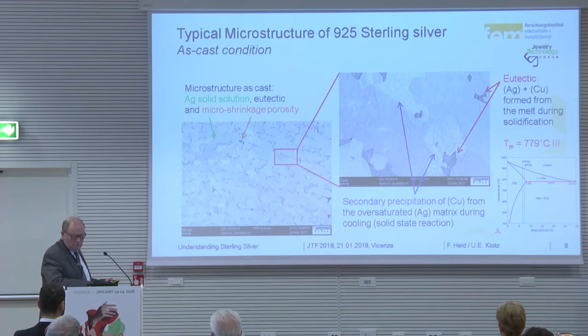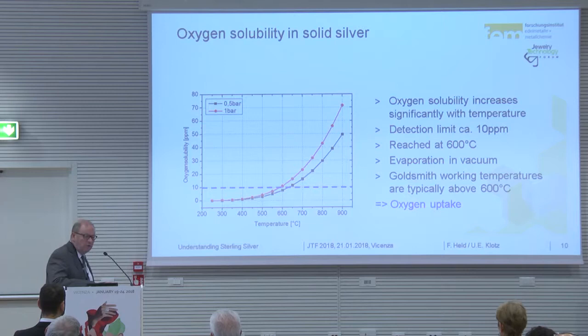What we most use is to look at how oxygen can be soluble in solid silver. We have the blue line here, which is what we can normally analyze. We can only analyze if the oxygen is higher than 10 ppm. If it is lower, we cannot analyze. Then we cross with about 600 degrees, and we see that the oxygen solubility in silver increases very fast, and we have 45, 50, 60, 70 ppm. It also depends on the pressure we work at.